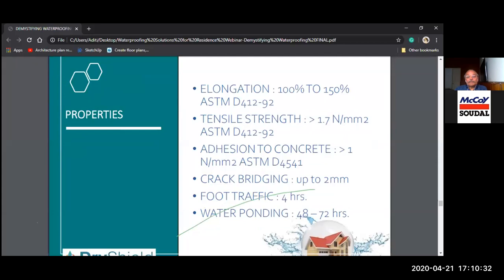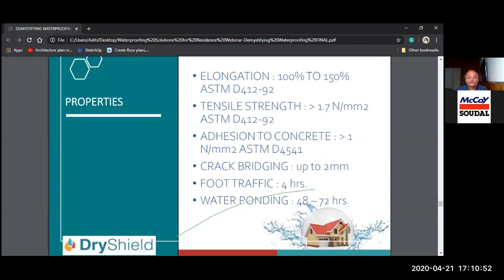The general properties are that elongation is 50 to 150% as per ASTM, tensile strength is somewhere around 1.2 to 1.7, and adhesion to concrete is 1 Newton per millimeter square. Crack bridging capacity is up to 2 mm because of the 50 to 150% elongation. Depending on the product, the best would be about 2 mm. This system is ready for foot traffic in 4 hours, and water ponding should be done in 48 to 72 hours.